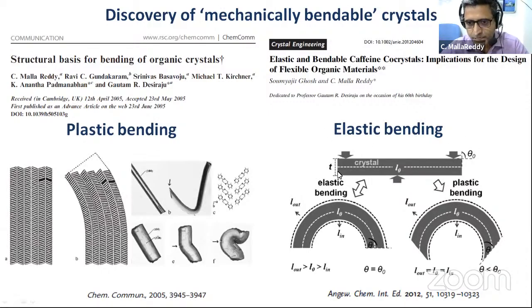So for example, if you look at this angle here, if you bend an elastic crystal, more or less you have a compression here, and then you have a tensile stress here. So you are basically pulling apart the unit cells here, and compressing the unit cells here. And then you have a distribution of the stress here, and the stress is not released in the case of elastic crystals. You don't see a big change in the interfacial angles at the tip of the crystal. But when you go to the plastic crystals, since there is a slip here, once you have a slip, the stress is more or less released. That is why you have a change in the interfacial angles, and that is what we found in most of these plastically bendable crystals, as you can see here. So this allowed us to explain the difference.